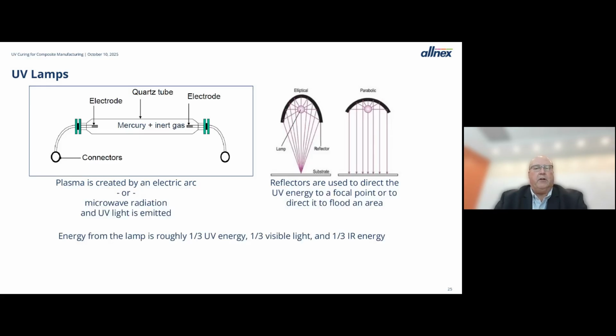And just to give you an idea of what these look like, you have a bulb with mercury and an inert gas, and you either form a plasma using an arc or microwave radiation. You can focus that energy using reflectors, or you can create more of a flood effect. And also understand that in mercury bulbs, the energy from that lamp is roughly 1/3 UV, 1/3 visible, and 1/3 heat. So there is some heat coming out of the front of a conventional lamp.